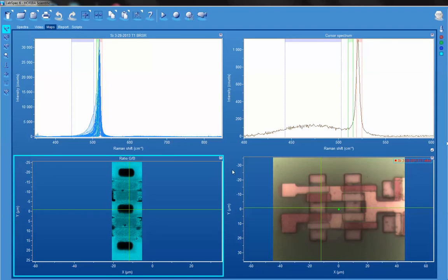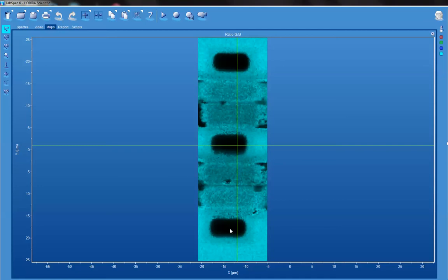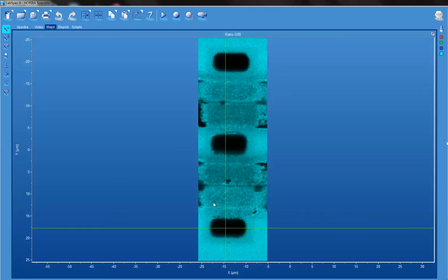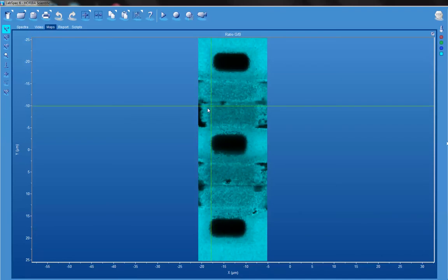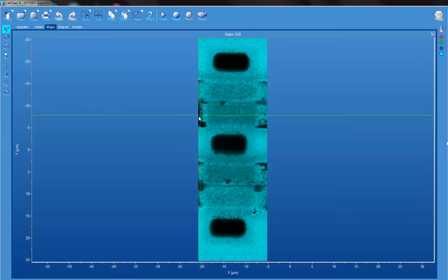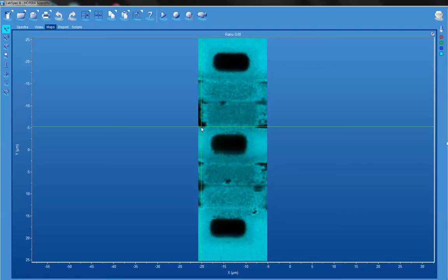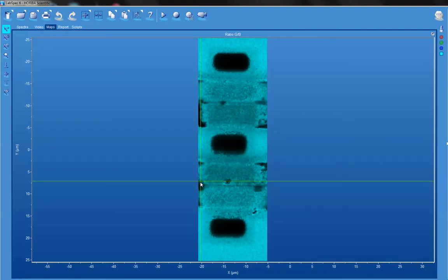Let's blow up this image again, just like we were looking at the green. Now you can see even more clearly the implant regions because they're so dark. Those areas of strain, both at the interfaces between the polysilicon and at the very edges of the polysilicon to the silicon substrate, show up very nicely by using these silicon band ratios.